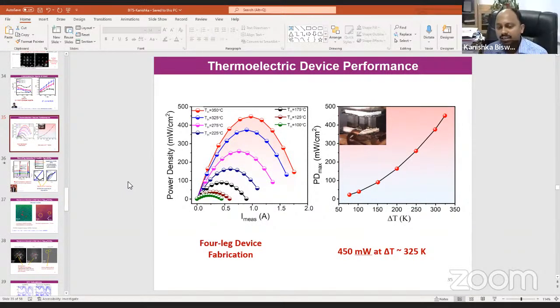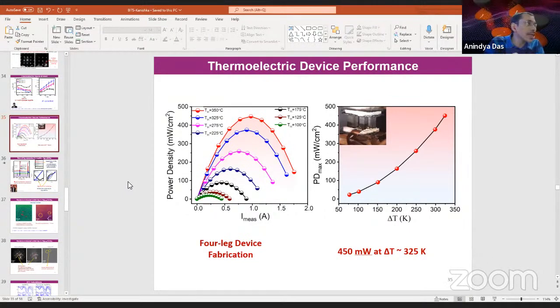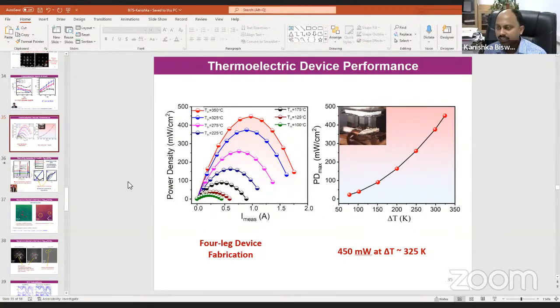It should help. The Moire pattern's periodicity has a size similar to the phonon mean free path, so it will also scatter a huge amount of phonons. But the periodicity should be in the nanometer range. If it is in microns, it may not help. Yeah. The phonon mean free path depends on temperature and varies from material to material. But generally, for high-performance thermoelectric materials like lead telluride, bismuth telluride, tin telluride, germanium telluride, selenides, or sulphides, the mean free path of the important acoustic phonons lies around 1 to 20 nanometer. So this is a game of nanoscience: how to scatter the phonons.